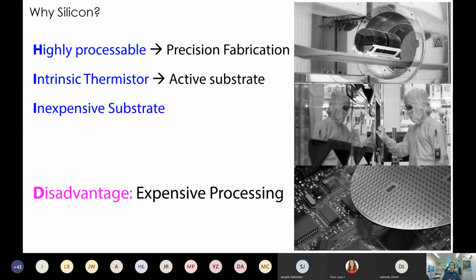In addition, silicon has many intrinsic properties that we can easily exploit. It's a semiconductor, so we can pass a current through it and easily convert it to a heater, like the heaters that you may use in your homes in the winter. But aside from that, because it's a semiconductor, its electrical conductivity is related to temperature. So if we measure the electrical conductivity of silicon, we can determine the temperature of our sample. So just as the material itself, without doing anything, it provides two of the important functions to be able to build a PCR-type DNA detection technology.